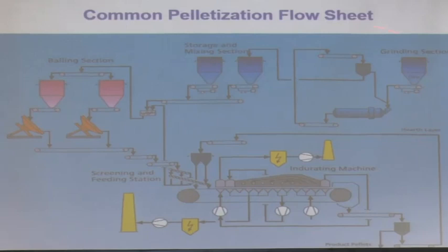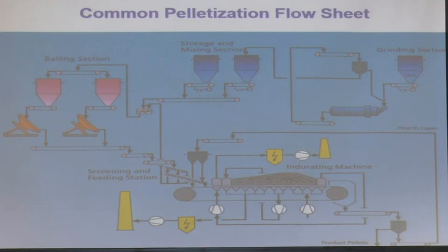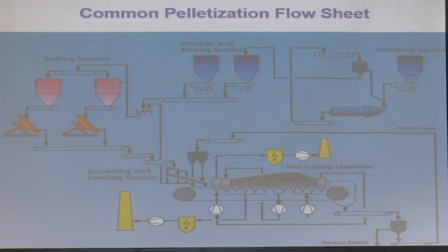If you look at the common pelletization flow sheet, it has three broad areas. One is grinding: the slimes at minus 150 micron have to be ground to below 63 micron, so I need a close circuit grinding operation with a cyclone. Then in pelletization there are two sections: one is the green ball section, where you make the pellet but it does not have sufficient strength. To make it stronger, I have to heat it — the water goes out and you need incipient fusion between the particles, similar to the sintering process with coarser particles.